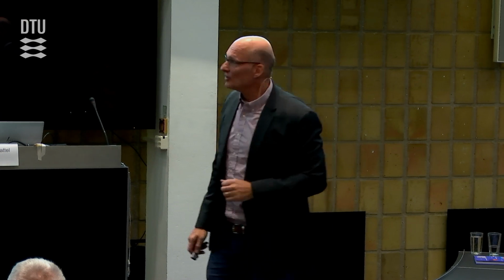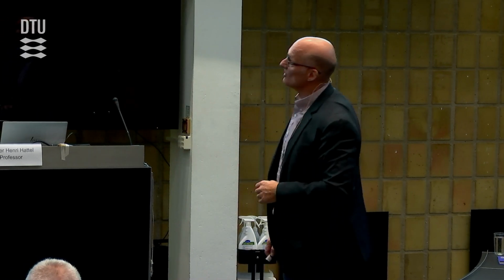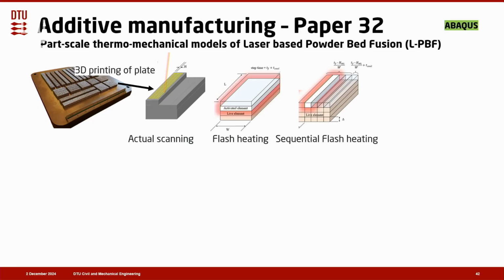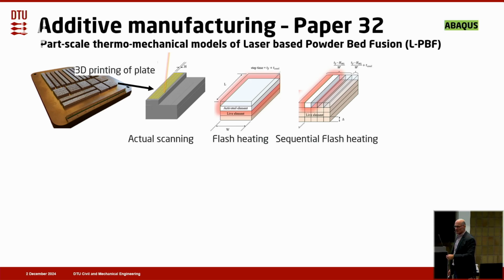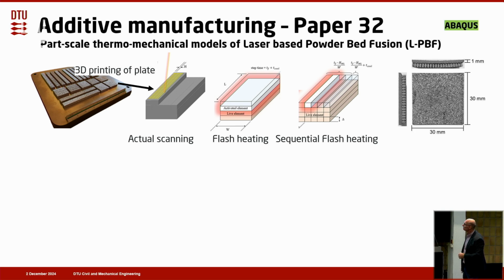Coming to paper 32, it was a part-scale thermomechanical model. Here you look at a 3D printing of one of these plates here in the corner. That's a rectangular plate. You have the actual scanning. And then what we used was a flash heating. This is where you lump a lot of layers and activate them at once. This means that the calculation time is highly reduced.